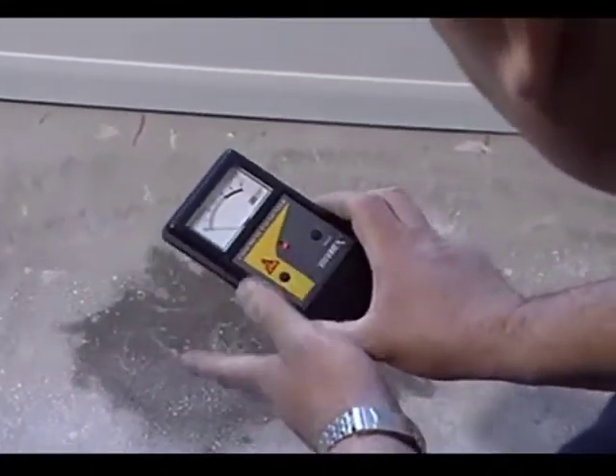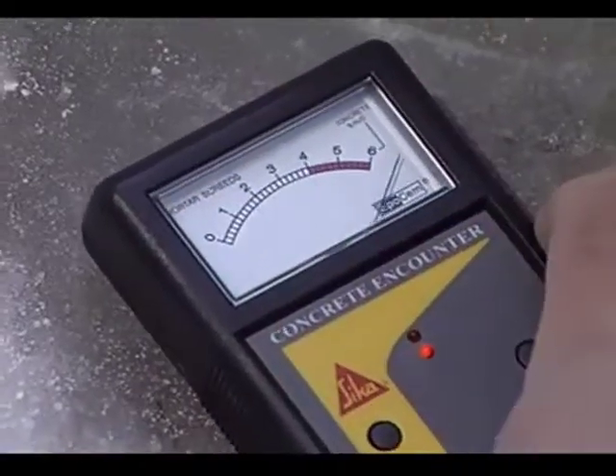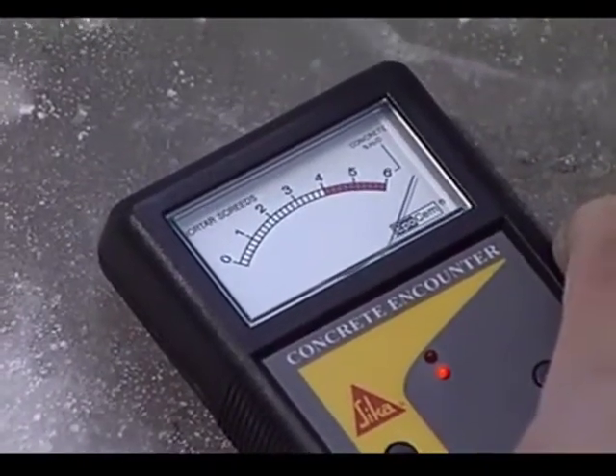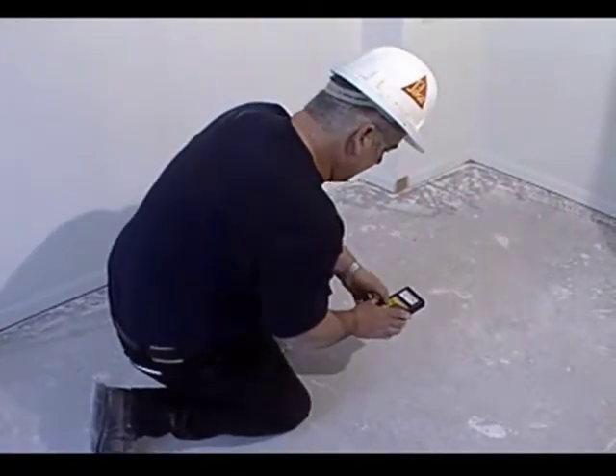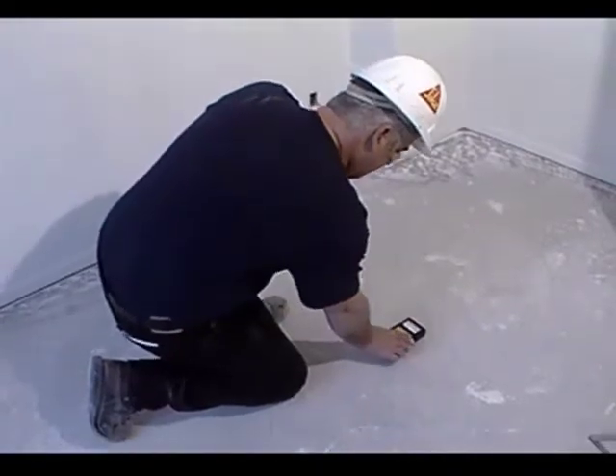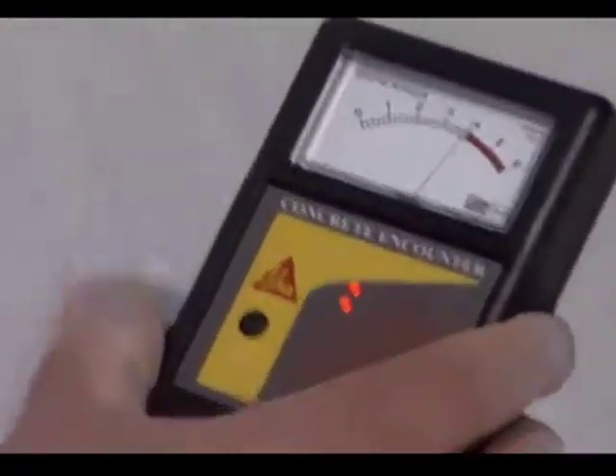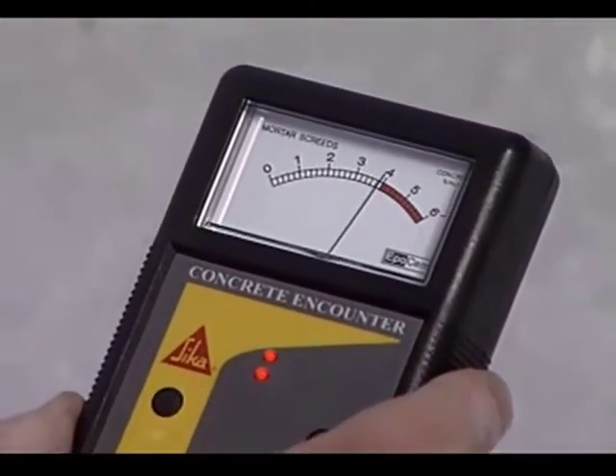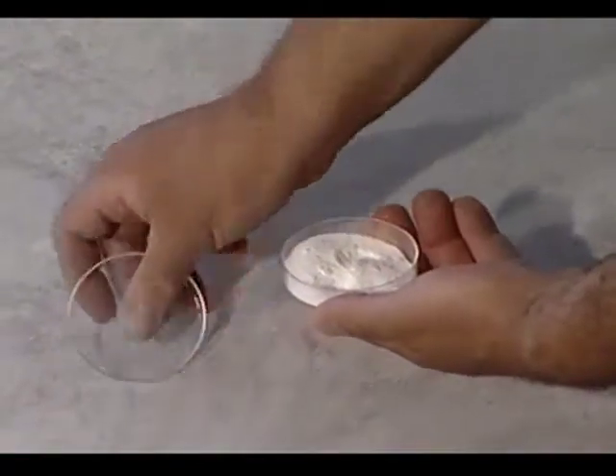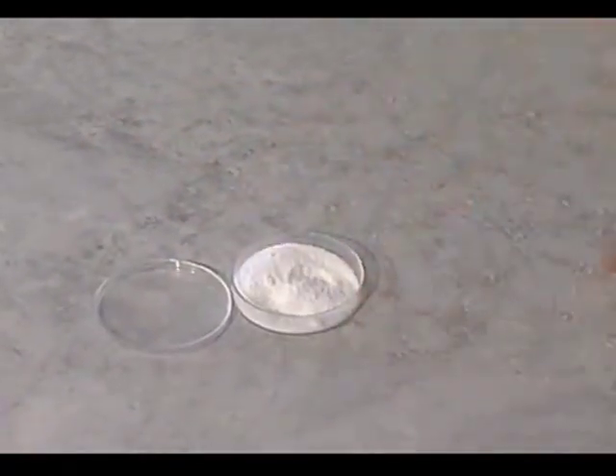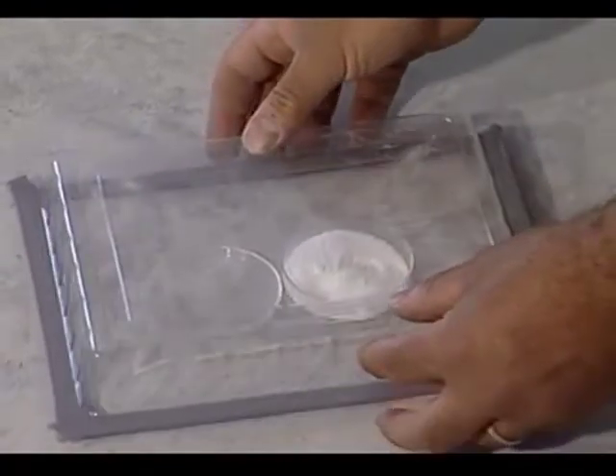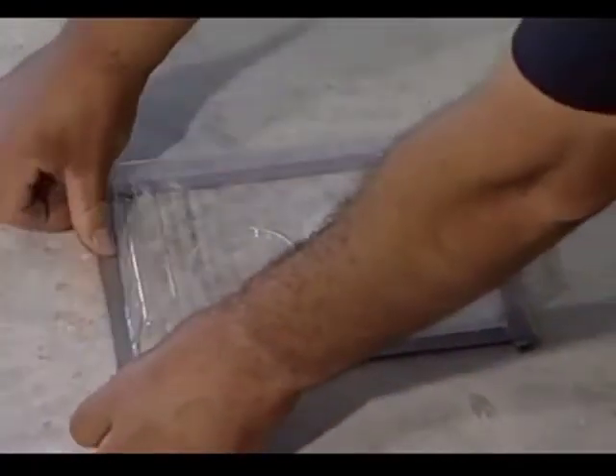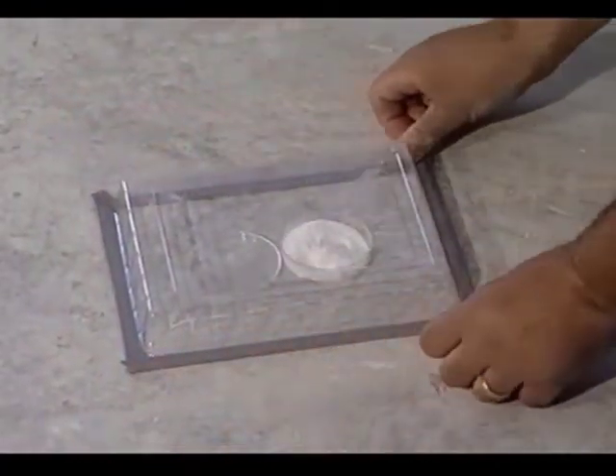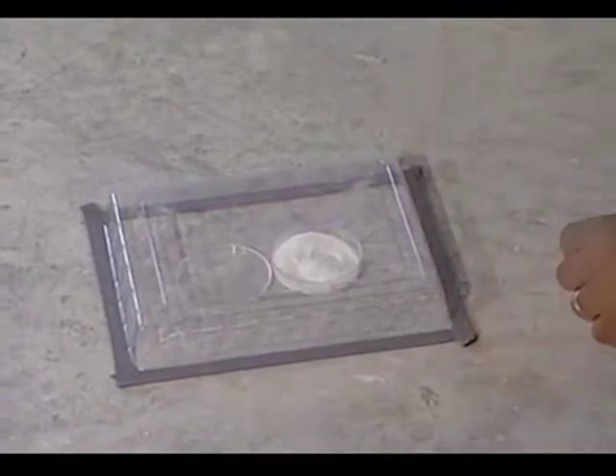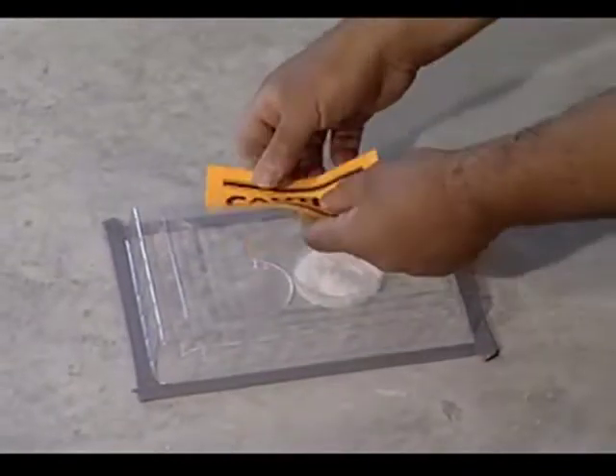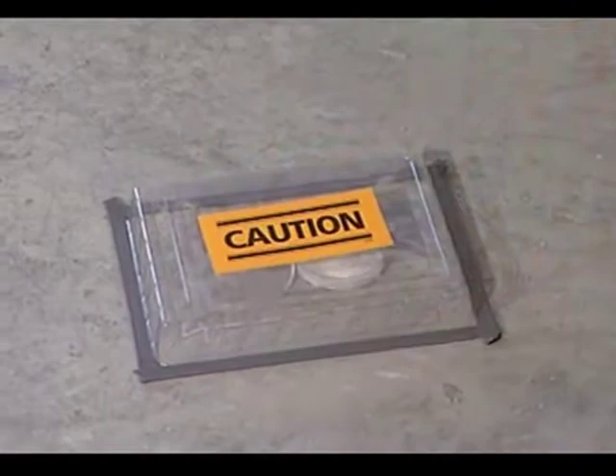The second method, Electrical Impedance Test, employs the Sika Concrete Encounter moisture meter. This instrument, when placed on concrete, will measure the amount of moisture in the upper region of the concrete slab. Any reading below 4% is acceptable. The third method, Calcium Chloride Test ASTM F1869, is used to measure the rate of moisture vapor emission from the concrete slab. An acceptable reading is 3 pounds per 1,000 square feet in 24 hours.